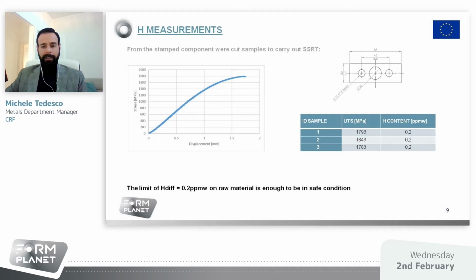After this characterization, having looked at what was the maximum value of diffusible hydrogen absorbed by the material, we carried out together with Latomec and the University of Pisa the slow strain rate test to see if this quantity of diffusible hydrogen could have an effect on the mechanical properties of the material.